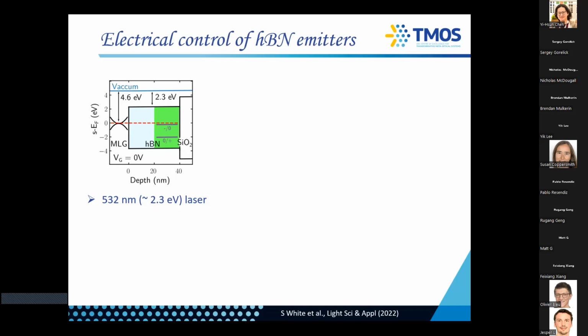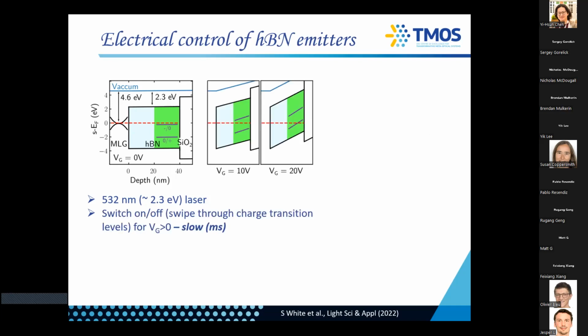The device is to scale, so we have a 20 nanometer capping layer and a 20 nanometer layer with emitters. When you apply positive voltage, you will see that one transition level crosses the Fermi level, so it will become optically active. Then when you increase the voltage even further, the second transition level will cross, and this transition level is not optically active. So it's basically a charge switching effect.